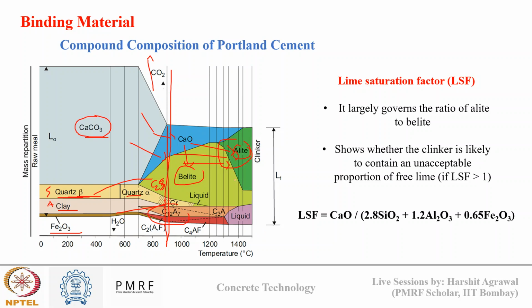And this is what I was telling you initially, when we talked about the difference between hydraulic lime and Portland cement. In hydraulic lime we are heating limestone only till 700 to 800 degrees Celsius. So if you see this line mark, up till 800 or even 900 degrees Celsius, there is only C2S present in the system. Whereas in cement there is C2S and also C3S. So this is the change in composition from hydraulic lime to cement upon further heating, and that's why Portland cement shows higher strength compared to hydraulic lime.